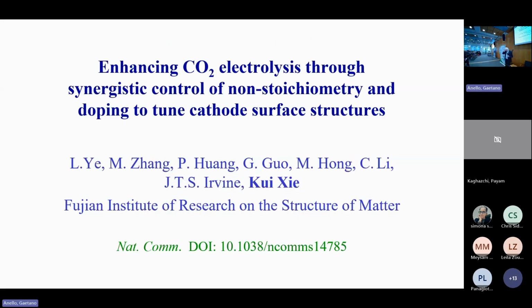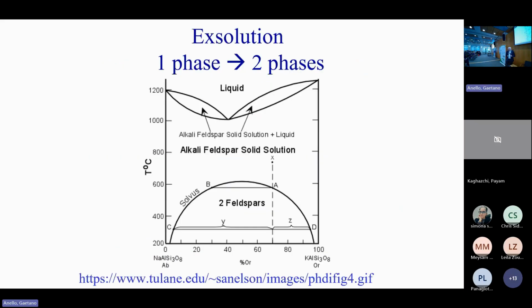So he completed his PhD, went back, and we spent some years collaborating on CO2 conversions. One of the things he was looking at was using exsolution materials. This is something that we developed, we've let loose in the world, and most of the stuff is not very good, actually. It's rather disappointing. It's not a magic thing. Exsolution is decomposition. As a chemist, I've been making lots of phases that decompose for many years. So exsolution is one phase becoming two phases. Sometimes it works very nicely. You have to think about that. This is from geology: feldspars under cooling separate from one to another.